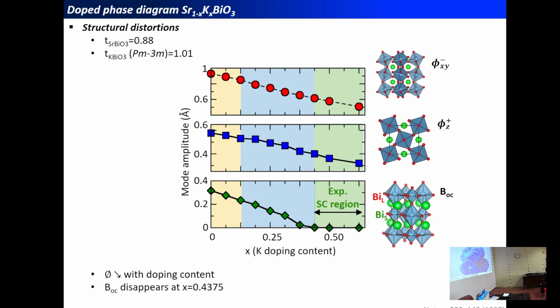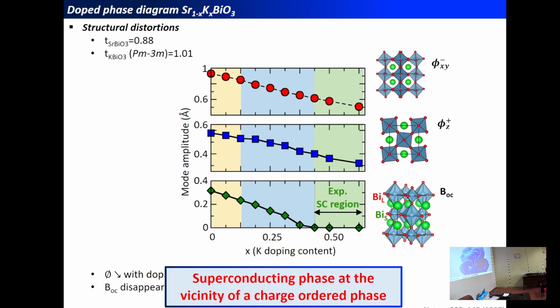And therefore, that's why it's decreasing, because the tolerance factor is going closer to the perfect value of 1. But now, what's interesting is that for the breathing distortion, what we observe is that across the different regions, at low doping content and intermediate doping content, this breathing distortion is still sizable in the material up till it reaches exactly 0 at 37.5% of substitution, where the superconducting region is appearing experimentally in the compound. And so these results, in agreement with the density of states, suggest that effectively in this region the two types of bismuth cations are becoming equivalent, and therefore we have no more charge ordering, and superconductivity is very likely appearing in the vicinity of a charge ordered phase where we would expect to have a charge density wave. So in these compounds, we expect effectively to be in the vicinity of a charge ordering. This is what's suggested experimentally.